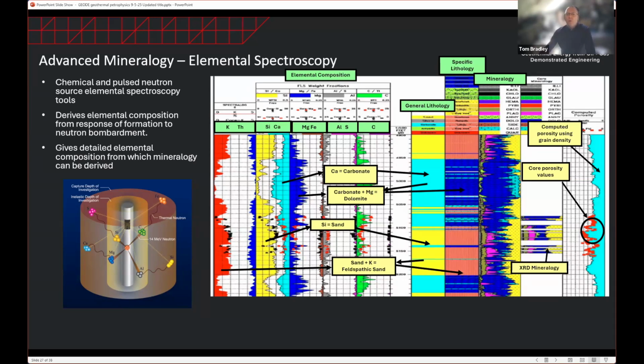And this is also useful because then it's telling us our mineralogy. I mentioned earlier, this is useful for things like predicting pore plugging, formation responses, and equally can help us with our density logs to get a confident formation density. Going back to the density porosity equation, one of the things we confidently need to know is our formation matrix density. By working out a detailed mineralogy, we can derive this. Hence, we can then derive a confident formation porosity, which is related often to permeability.